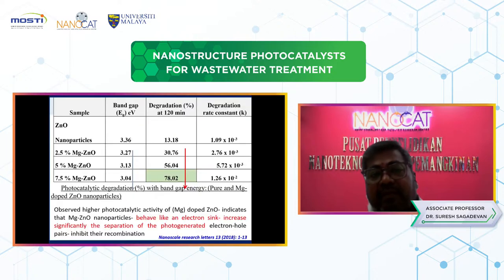You can look at here the bandgap value versus the degradation percentage, as well as the degradation rate constant. From this table, you can clearly see that the bandgap values decrease, increasing these degradation percentages. The maximum degradation percentage is shown by the 7.5% Mg-doped zinc oxide nanoparticle.